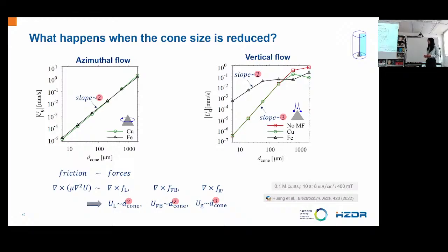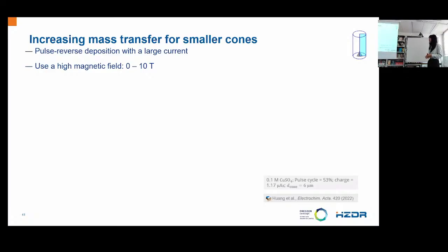that corresponds to the simulation. So this scaling law could be quite useful because optical measurements, they could measure the flow of a cone or similar structure at millimeter or large micrometer size. And by applying this scaling law, we could get an idea of some order of magnitude for the flow around the similar structure, but at nanometer scale. So we see that with smaller cone size, the beneficial flow is getting smaller, which can be expected.